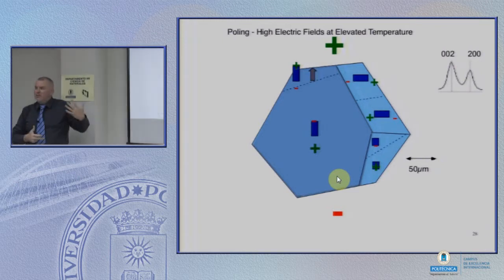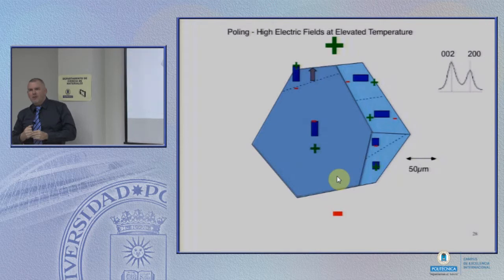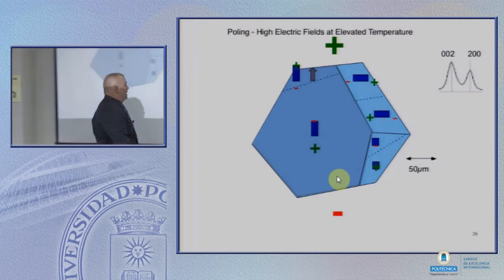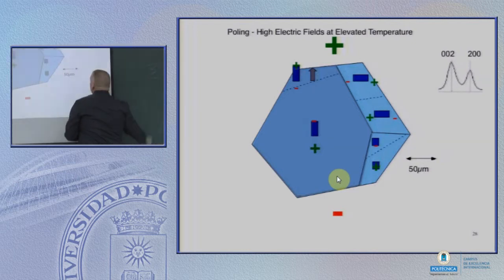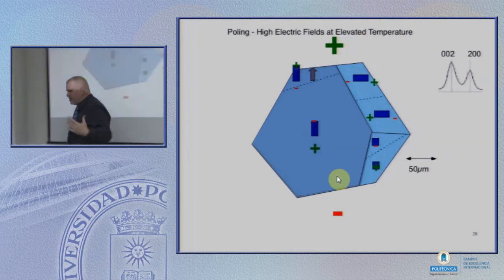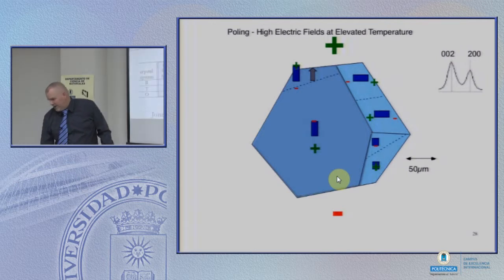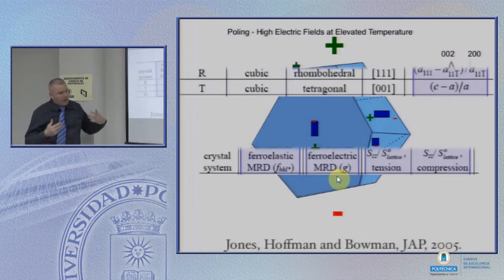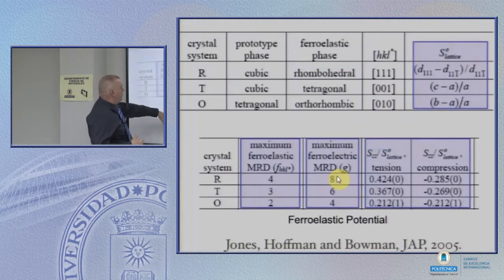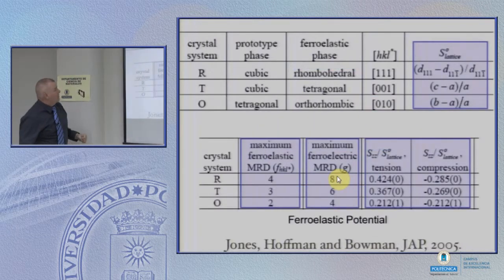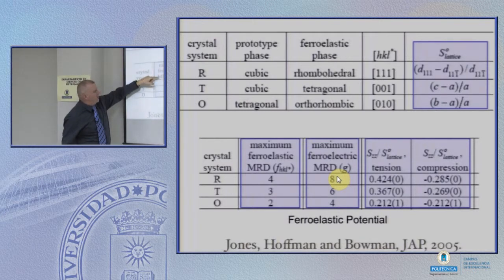It turns out the maximum value for what we call the multiples of a random distribution, which is MRD, the maximum amount we can have of that is 3, okay? So we do a calculation that's based off of that, and we can look at that relationship. If we look at different crystal systems, this is from a paper in 2005 that we did. We look at a rhombohedral material, tetragonal material, and an orthorhombic material. We can define the characteristics of the strain, a lot of the details, but the ferroelastic MRD, this term that I described there,